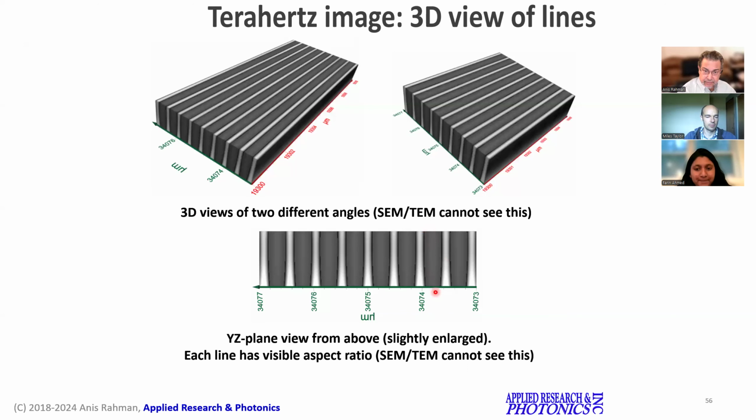So as you can see, with this kind of aspect ratio, these lines went a few micron deeper into the silicon, but they are narrower on the top and wider at the bottom. And this happens because making the channel inside the silicon is not all that easy. But if we looked at only the surface, then we would not know how the structure is at the bottom.